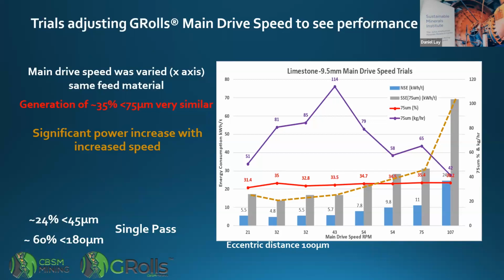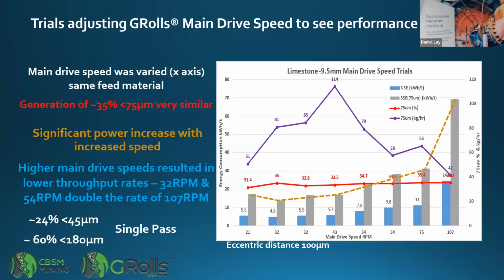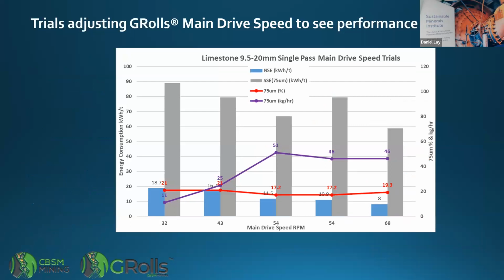So for each of the materials, you do a whole lot of work on it. And this is the revolutions, the main drive speed. What you try and do is match the amount of oscillations of the gyration against the main drive to get that shearing, tension, and compression as much as possible. When we did, that previous slide was for minus 9.5 mil.